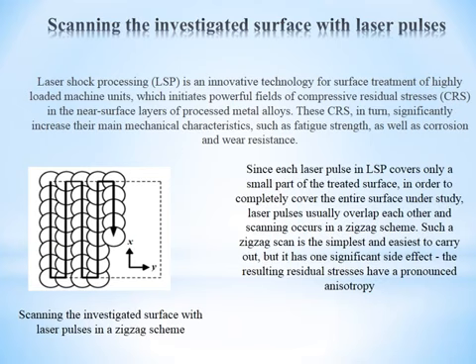Only recently was the effect of LSP on the generation of dislocations, the nature of displacement of dislocations and grain refinement studied in depth, and it was suggested that it could be related to the anisotropy of residual stresses. However, more systematic studies are needed to explain the anisotropy of residual stresses.